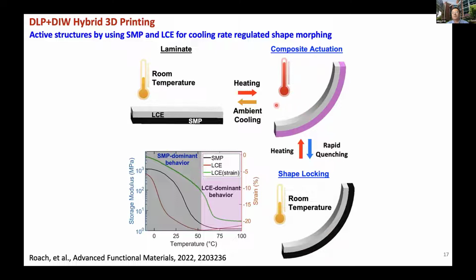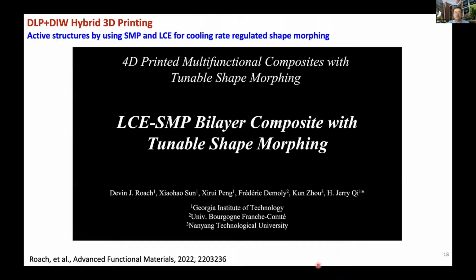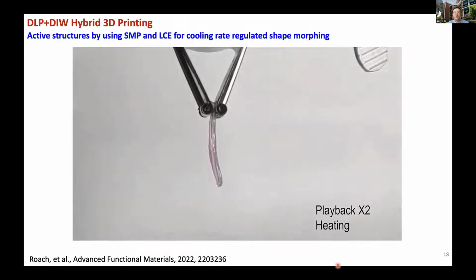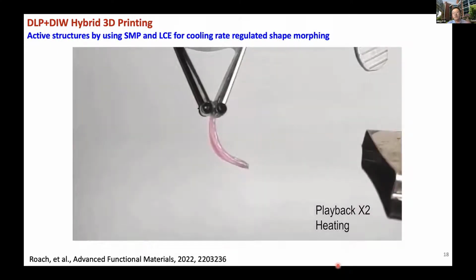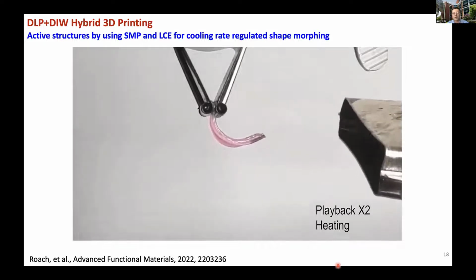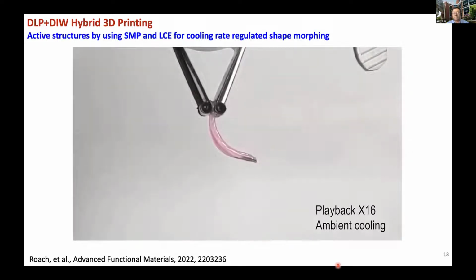So if you do an ambient cooling, it comes back. If you do a quench, it can go this way. So you can actually branch the shape depending on your cooling rate. Here shows one experimental demonstration. Here's a strip with LCE and SMP. Here we're using a thermochromic dye in the SMP. So when the temperature is up, you can see the color become sort of pink. When you cool it down, it becomes black.